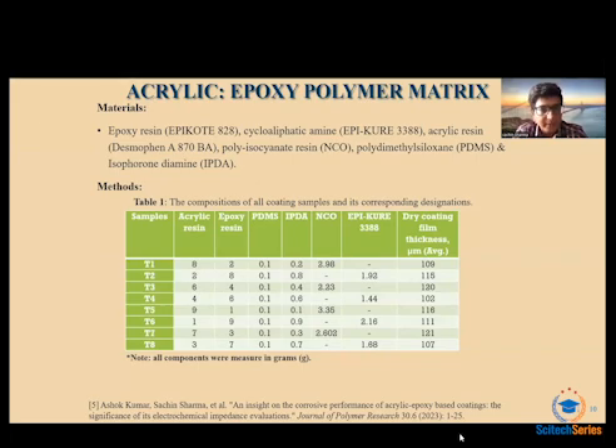So we have T1 up to T8 samples, and we can see that the acrylic resin to epoxy resin, we had varied the ratio, from 8:2 to 2:8. So all these were measured in grams, and we kept the PDMS inclusion consistent, which was 0.1 grams. And the IPDA calculation was based on the amount of epoxy used. So 1 to 10 ratio of the IPDA to the epoxy resin used. And then polyisocyanate was used for those samples that contained higher content of acrylic resin. And of course, the Epicure 3388 was included for those samples that contained higher content of epoxy resin. And then using an Elcometer 456 gauge, we actually evaluated the thickness of the coatings for each sample in micrometers.